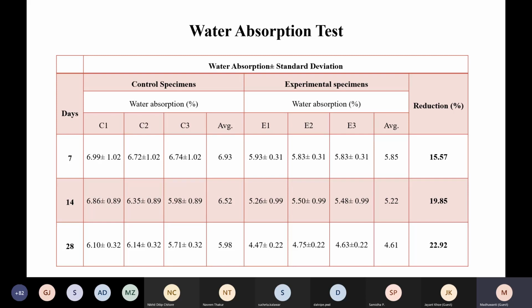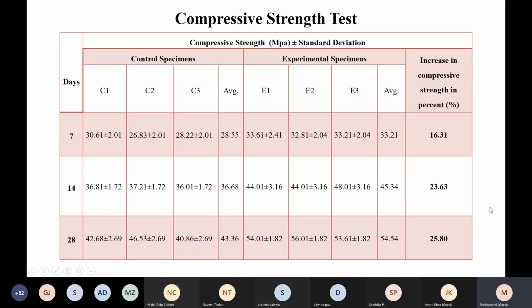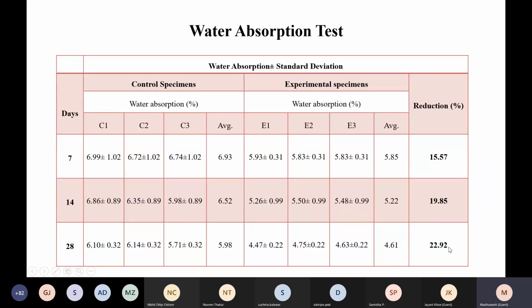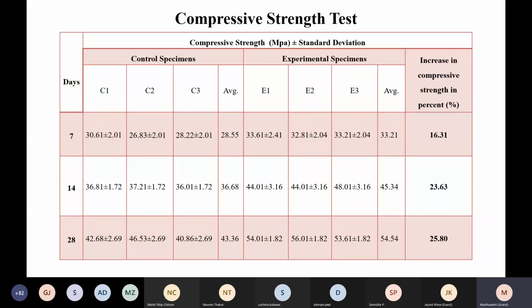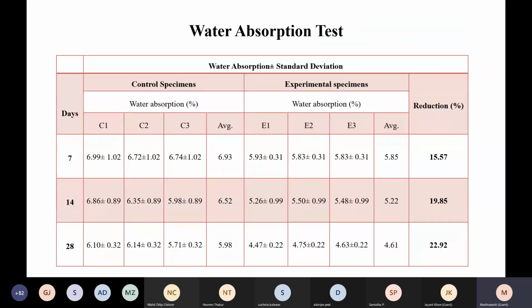So as you can see that on the 28th day, the increment in compressive strength was 25.8%, almost 26%, and the reduction in water absorption was almost 23% in the biocemented specimens as compared to control specimens. So this is quite a remarkable number in increase of compressive strength as well as decrease in water absorption.